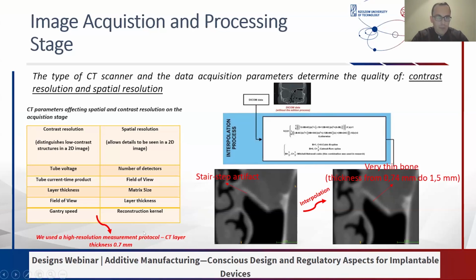to choose the most accurate measurement protocol, but then after we get the data, we choose the interpolation process on the data to minimize this effect. So now it is an isotropic structure and we also change the voxel size to 0.4 for the pixel size and layer thickness, not 0.7. So we have a more accurate representation of this area.